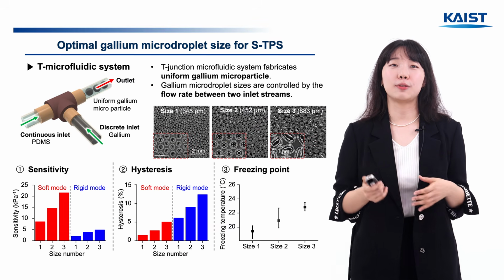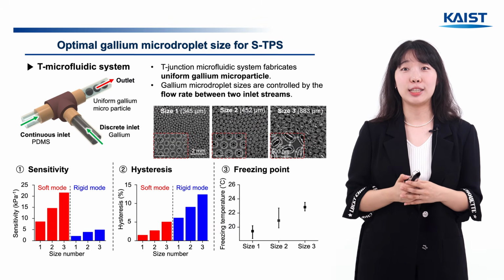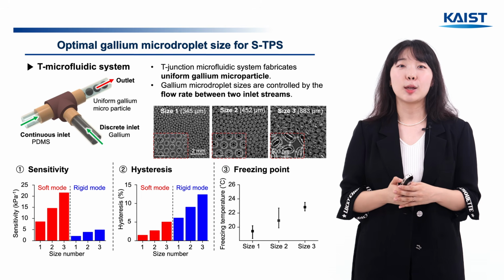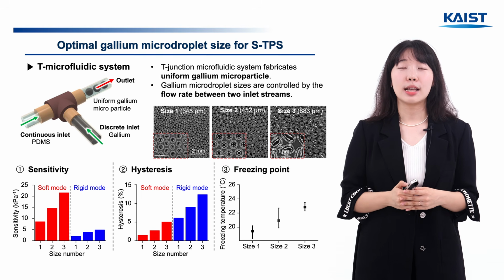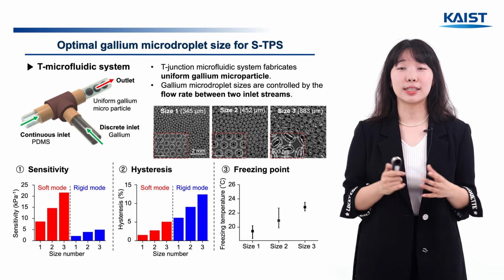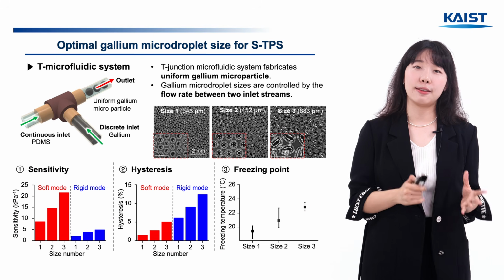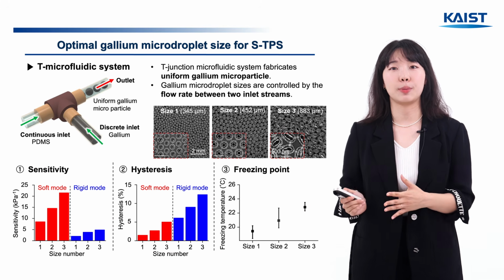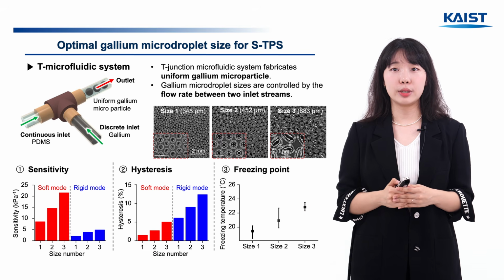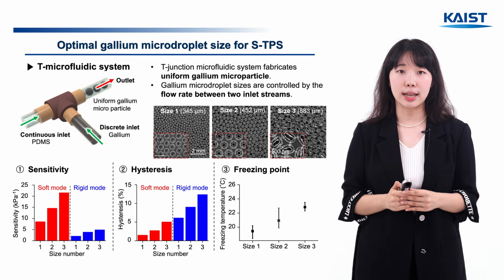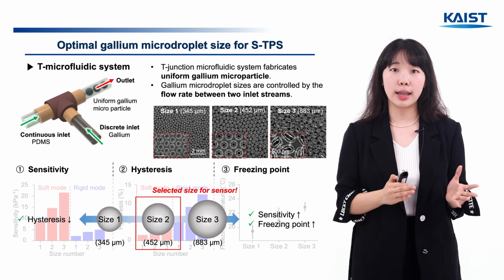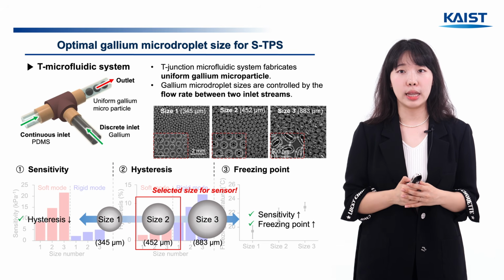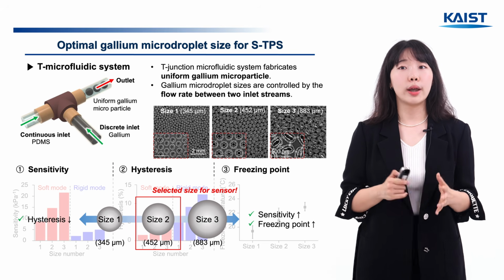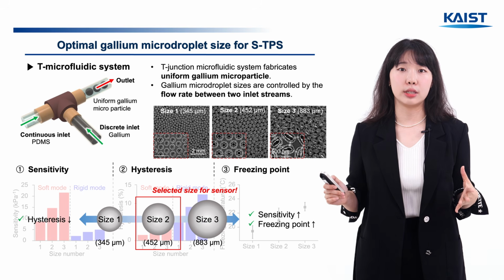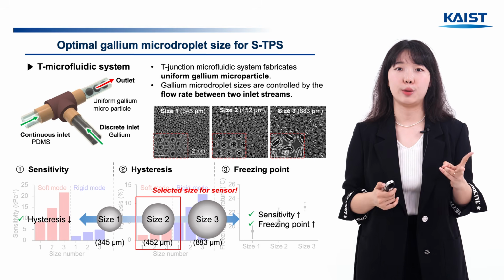By adjusting the flow rate at the inlets of the T-shaped microfluidic channel, the particle size can be controlled. So I made a sensor with 3 different sizes and compared their sensitivity, hysteresis, and freezing point. All 3 values increased with larger particle size. So, size 1 had a drawback of low sensitivity and low freezing point, while size 3 had high hysteresis, which is why I chose size 2.